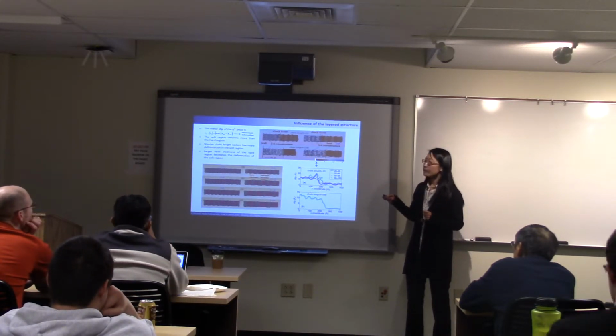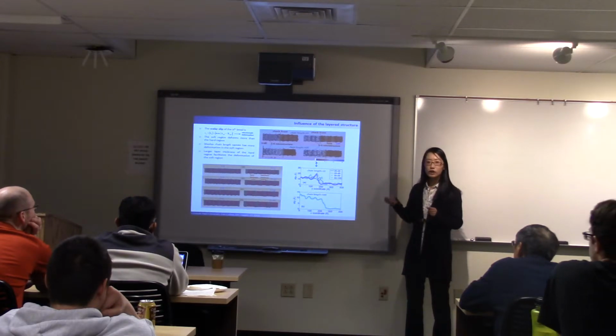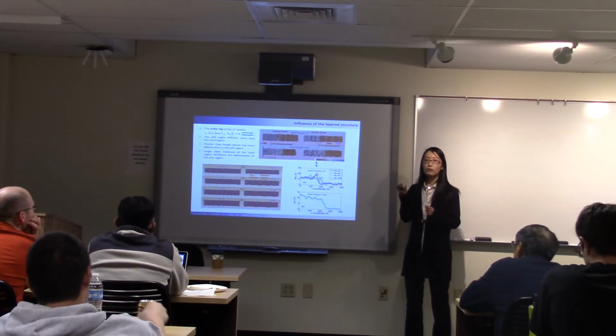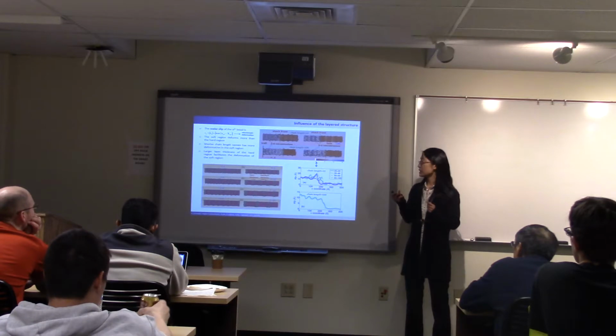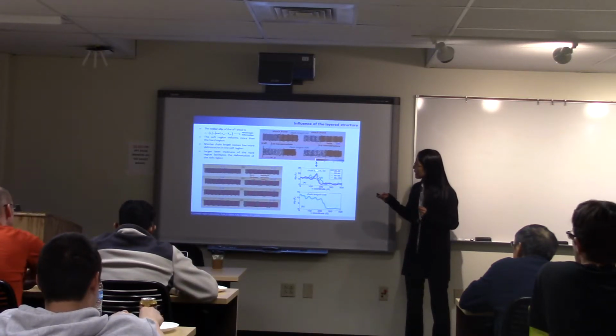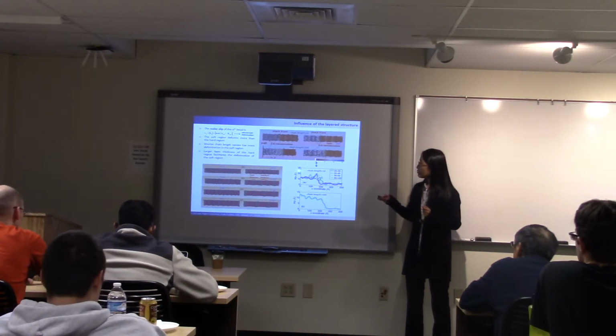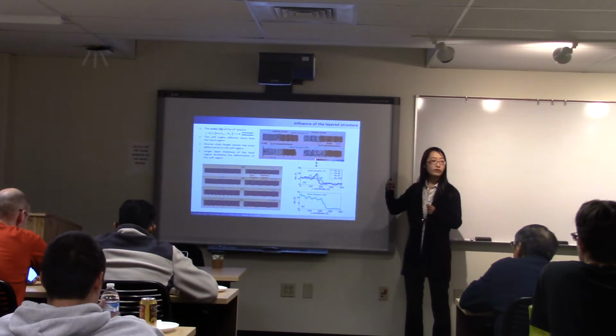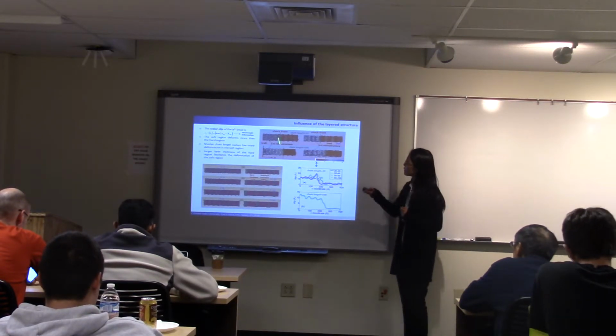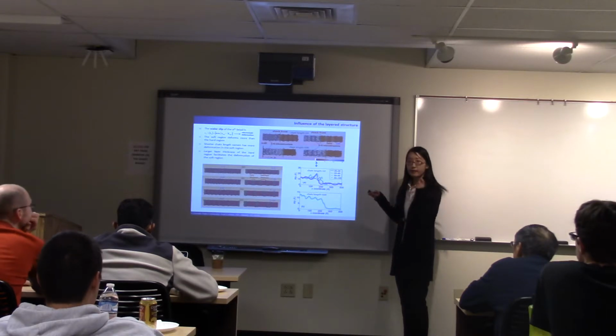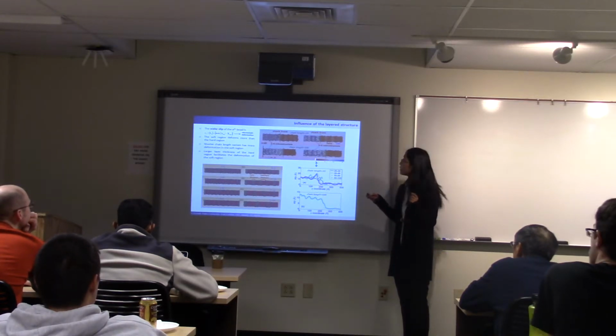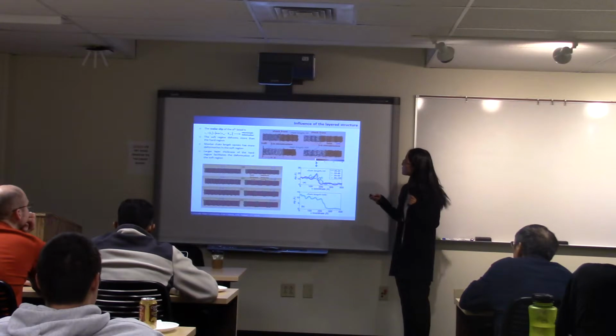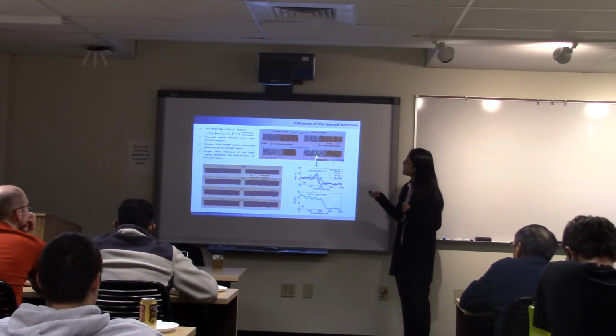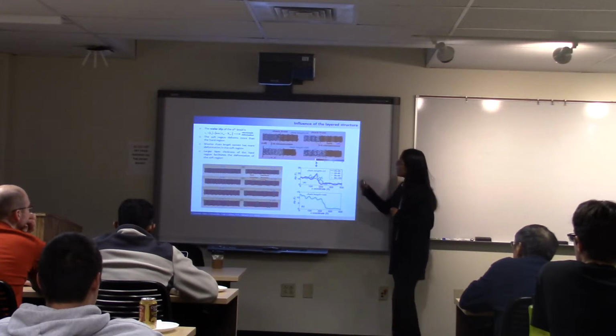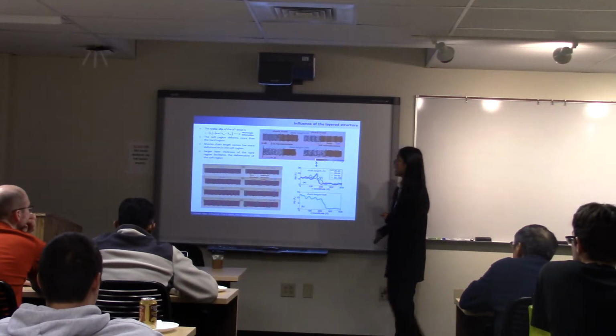We find this kind of layer structure promotes deformation in the soft part, which could absorb the energy. Also, when we have a shorter chain length, the deformation in the soft part is further enhanced. We also compare two different layer thicknesses of the nanoparticle containing region, and find that increased layer thickness will further promote deformation in the soft part, as seen by the contrast in color here.